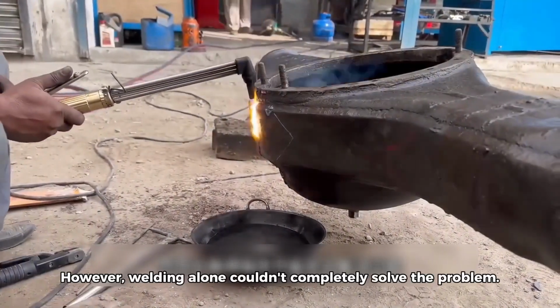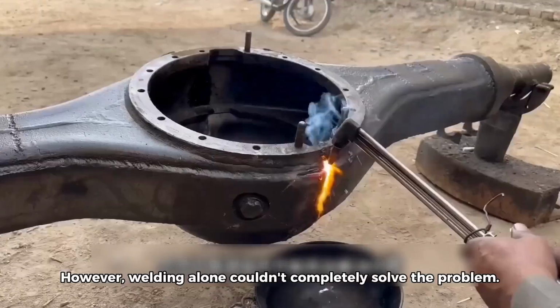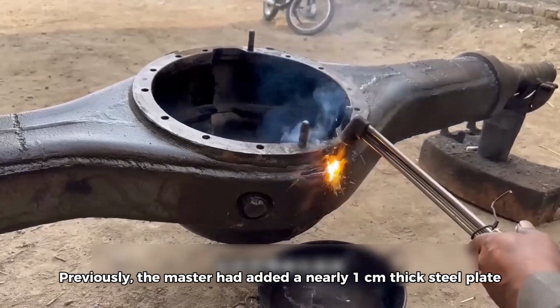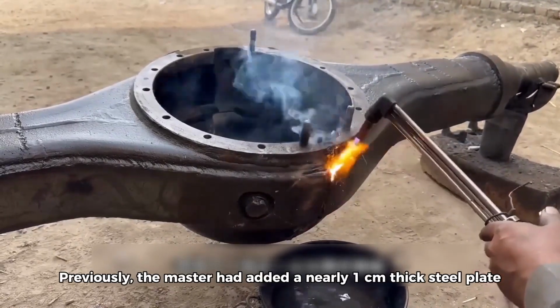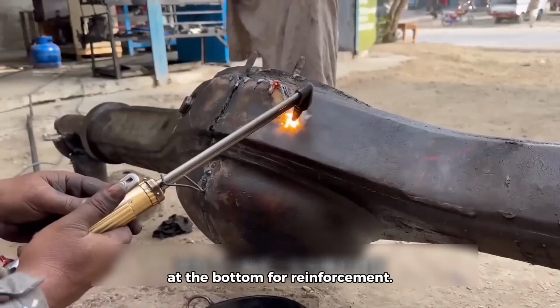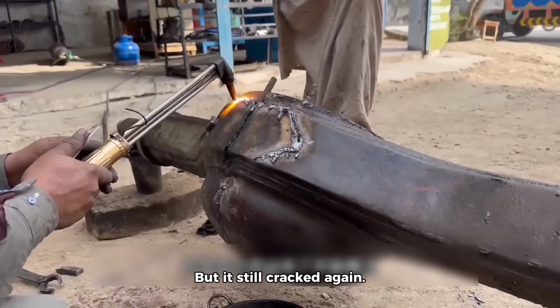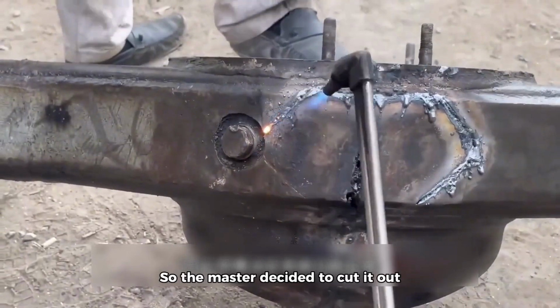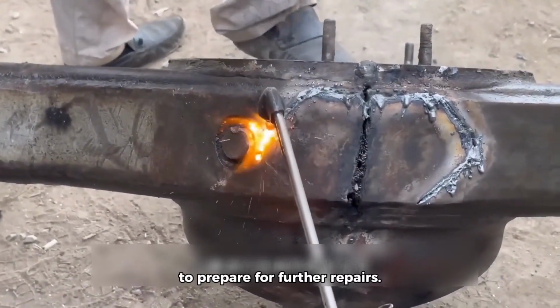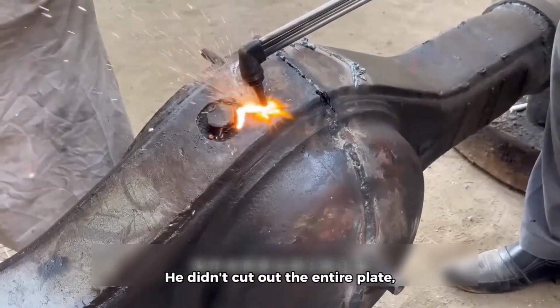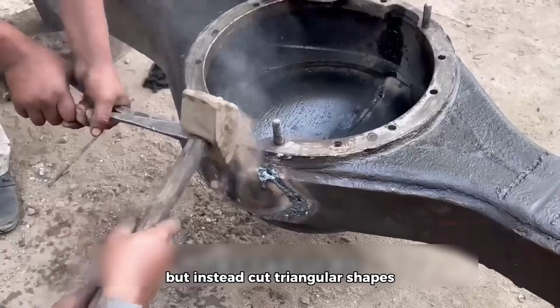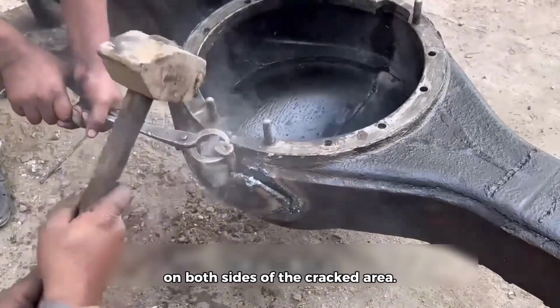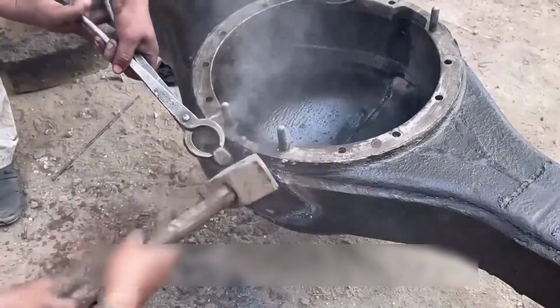However, welding alone couldn't completely solve the problem. Previously, the master had added a nearly 1 centimeter thick steel plate at the bottom for reinforcement, but it still cracked again. So the master decided to cut it out. To prepare for further repairs, he didn't cut out the entire plate, but instead cut triangular shapes on both sides of the cracked area.